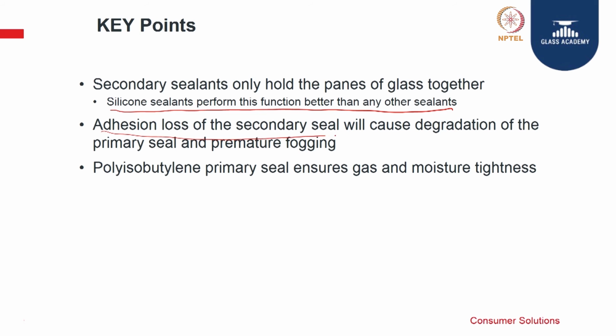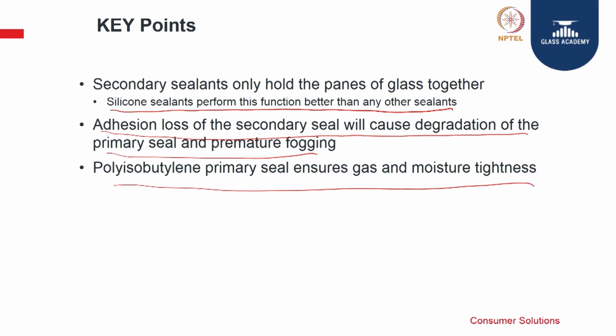Adhesion loss of the secondary seal will cause degradation of the primary seal and premature fogging. So, any other chemistry which can lead to adhesion loss in the secondary seal, the load will come onto the primary seal and it will fail, and there will be premature fogging. Primary seal ensures gas and moisture tightness.